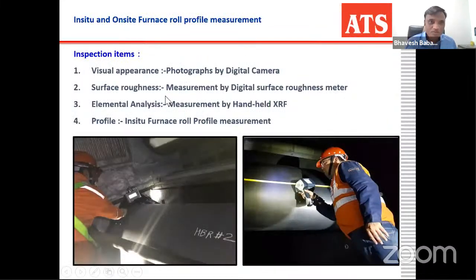Also, we do in situ roll profile measurement, because it is a prediction of the roll life. Removing any furnace roll from the furnace is a time-taking job, and it's not an assumption of the time. So we go inside the furnace with our instrument in in situ condition and check the roll profile. If any profile has deteriorated, the profile graph shows how much it has deteriorated and how long it may run. It may need removal in 2 months, 3 months, or 5 months. We get the exact idea once we check this profile. We mainly do this type of profile measurement at Tata Steel, JSPL, as well as JSW.